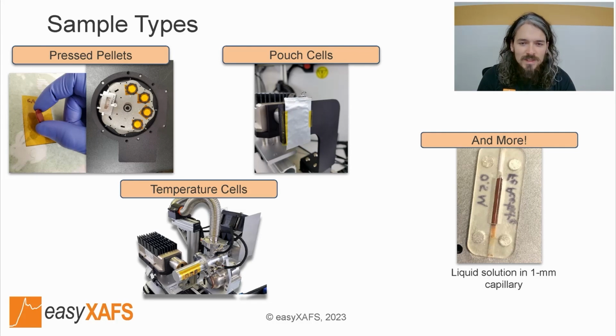It's also possible to have special environments for the sample, such as this cold stage that we customized for our system that can cool samples down to around 40 Kelvin during measurement. So this is commonly done at synchrotron beamlines, and it increases the amplitude of the extended XAS signal. Other types of samples can also be measured. So for example, here we have a liquid in a thin-walled 1 millimeter capillary. And depending on the sample composition and measurement mode, you can also use other preparations.